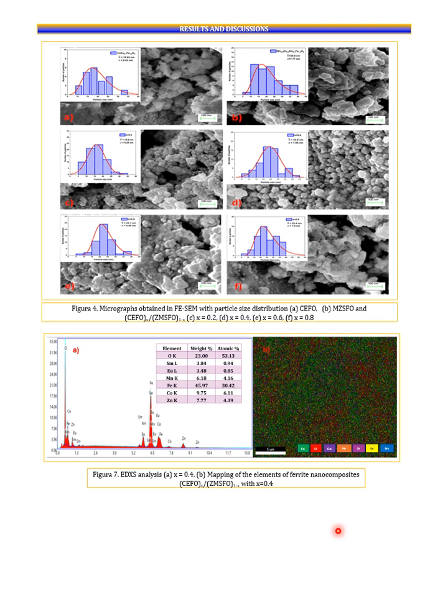These analyses evidence the presence of all the elements of the nanocomposites, confirming the successful formation of the desired compositions and that the lowest percentages are those of the rare earths, which is what is expected. All this supports the effectiveness of the preparation procedure employed.